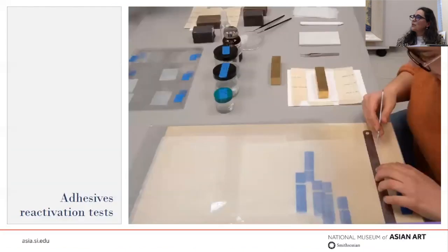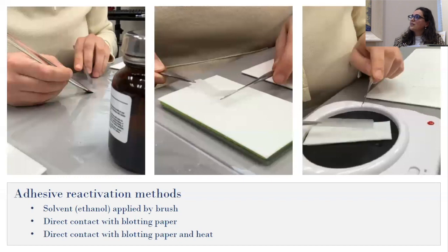Next slide, please. So when all the materials were prepared in a remoistenable form, we decided to conduct some reactivation tests. Next slide, please. So, the reactivation test method. We used 3 different types of reactivation methods according to the adhesive that we selected. For Klucel M and HPMC, we used solvent, ethanol, directly applied by brush because we didn't have any issue. But for the water-based adhesives, in the case of starch, we used a very slightly damp blotting paper where we laid the strip of our material. And for gelatin and isinglass, we also used a blotting paper, a little bit damp, in order to reactivate the adhesive.